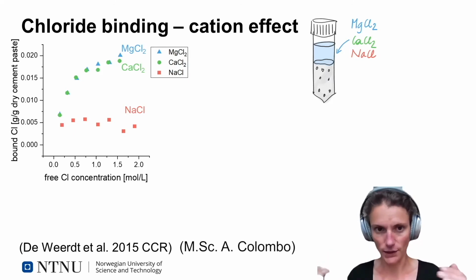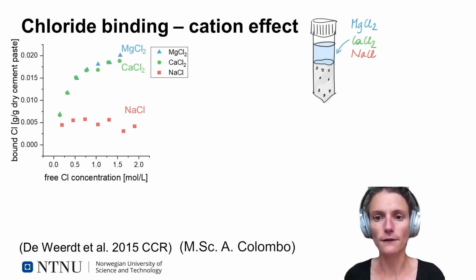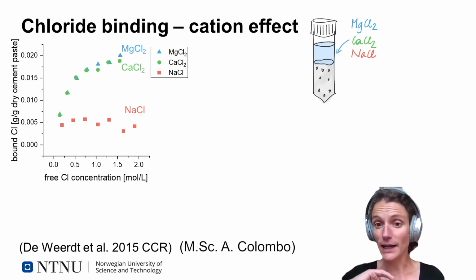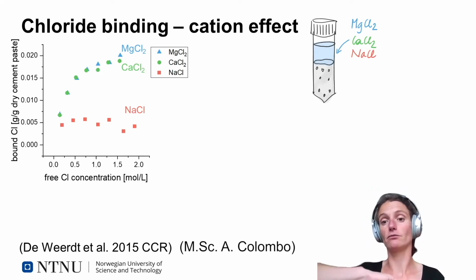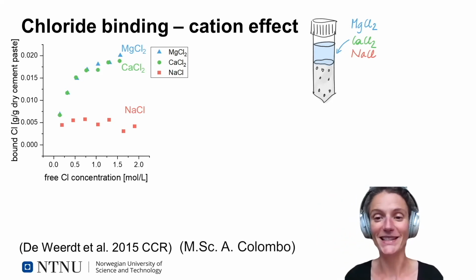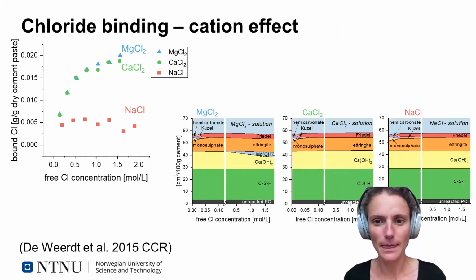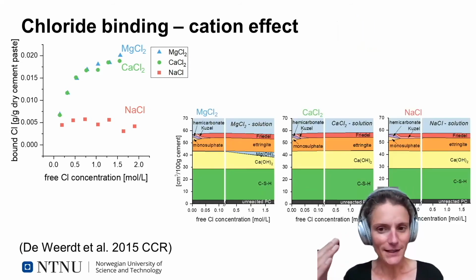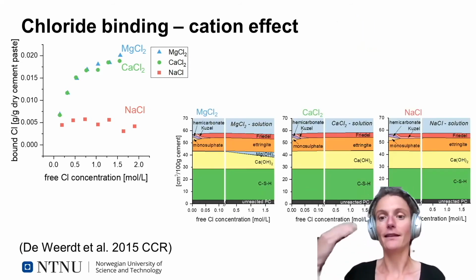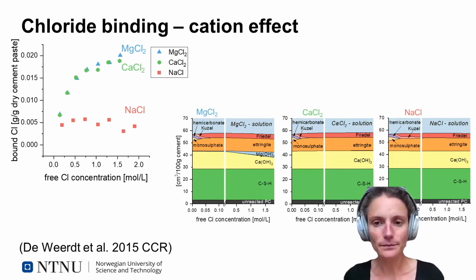So what we can see from this graph is that for sodium chloride, we are in a way for all these concentrations on a plateau. There's not a large difference in the chloride binding depending on the concentration. Whereas in case of calcium and magnesium chloride, we see a considerable increase when you're increasing the chloride concentration. So why do we have this difference between sodium chloride and calcium and magnesium chloride?